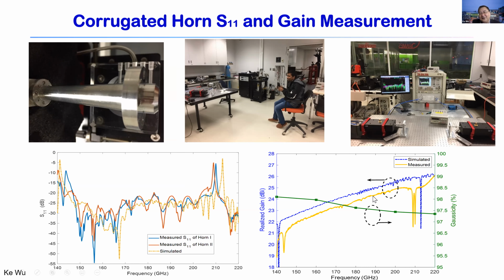Of course, it gradually increases as the frequency increases. That's very normal for any antenna. But on the other hand, at 210 gigahertz you have a drop here, and both simulation and measurement confirmed the value. You have a certain defect in the structure. We know that because of the fabrication defect, so we made the simulation to see how it works. Indeed, the measurement confirmed it.